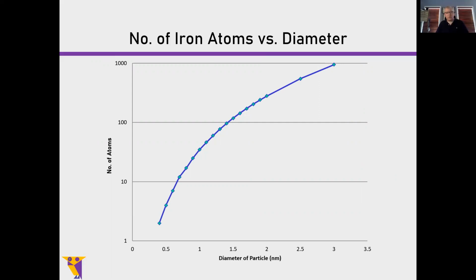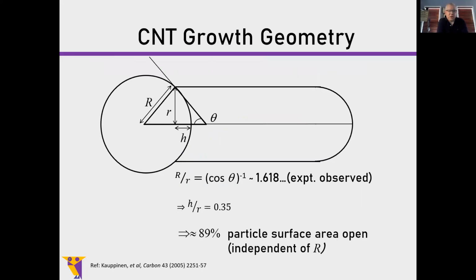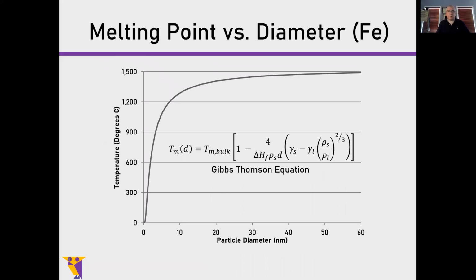And why that number is important is because there's a relationship between the nanotube and the nanoparticle that grows it. The ratio of the diameter of the particle to the diameter of the nanotube is 1.618. And that's a very interesting number. If anyone knows what that is, you can tell me at the end of the talk. But it is a number that occurs very frequently in nature. So if you have a particle that's about 1.5 in diameter, you're going to start making nanotubes that are about a nanometer in diameter, which are small enough to make single walls. So you can still use classical thermo to describe the processes going on with these little drops.